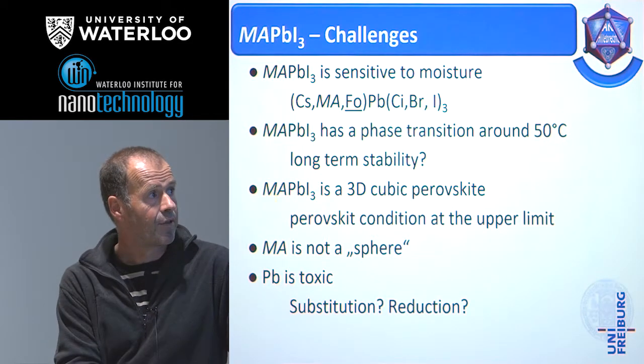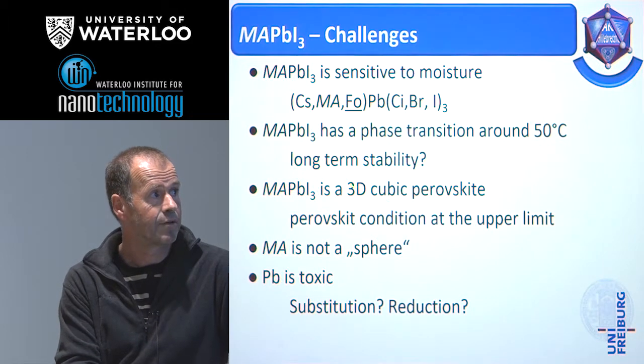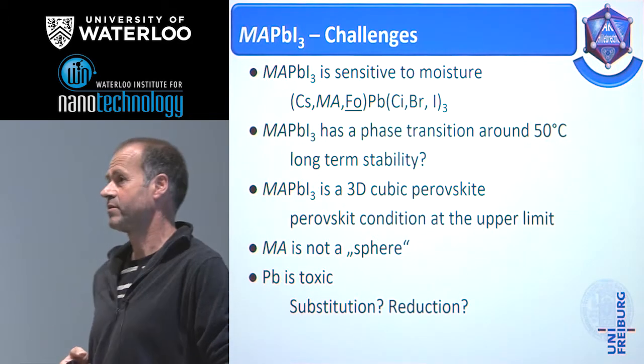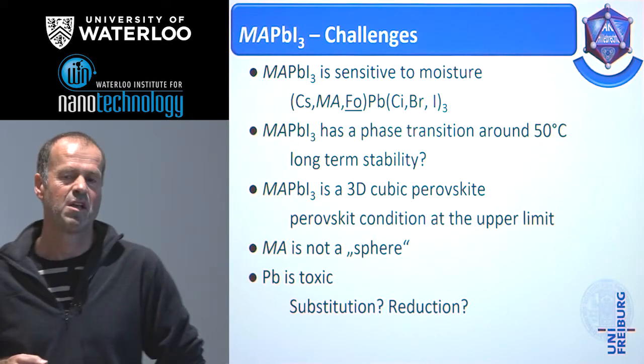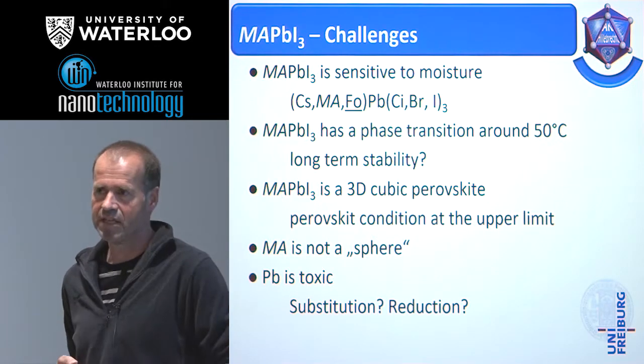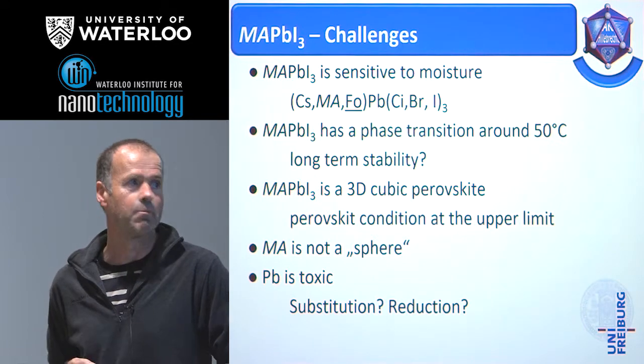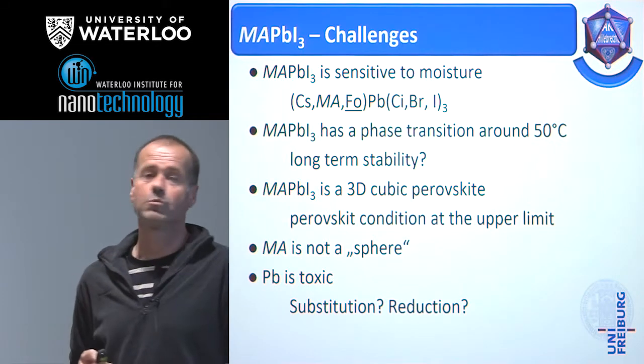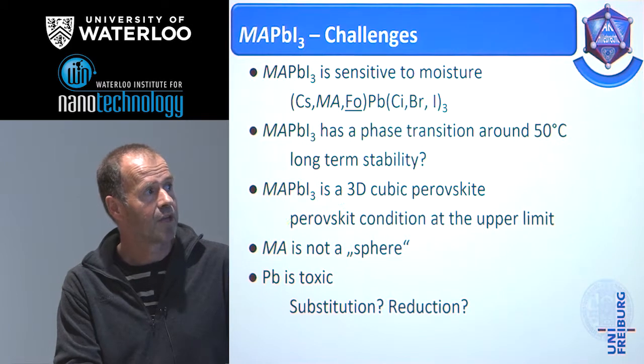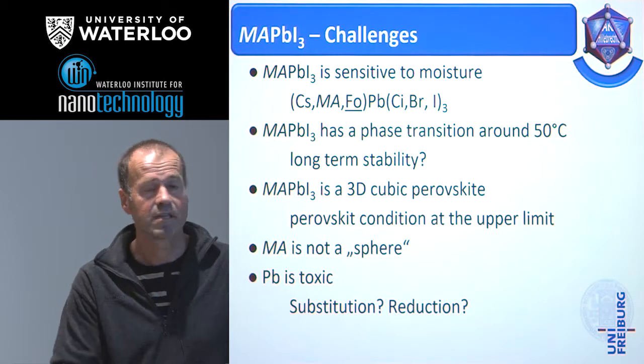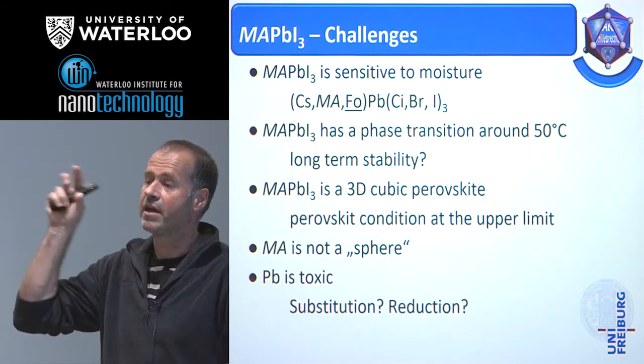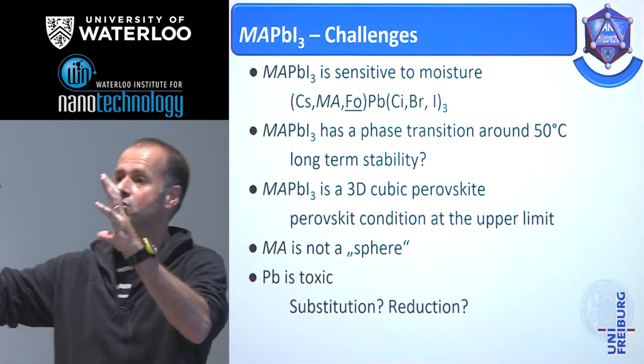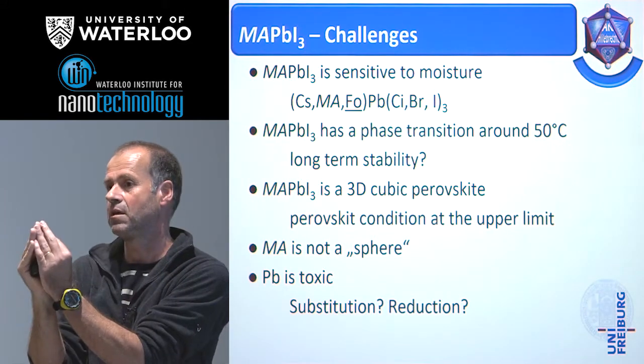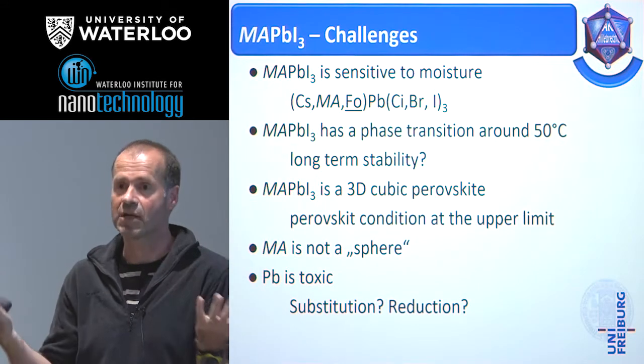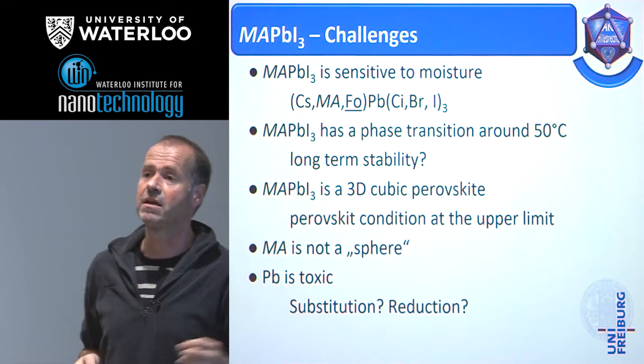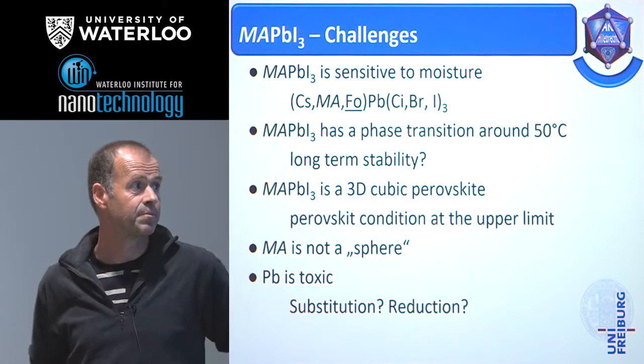Third point, the lead compound is a 3D cubic perovskite. At first moment it sounds not very interesting that it is a three-dimensional perovskite, but if you have a more or less cubic perovskite, you know that there is a perovskite condition, and there is an upper limit of the size of the cation. Because you have a three-dimensional structure, this size is limited. If it is too big, you need another structure, because otherwise the cation will not have the right space.